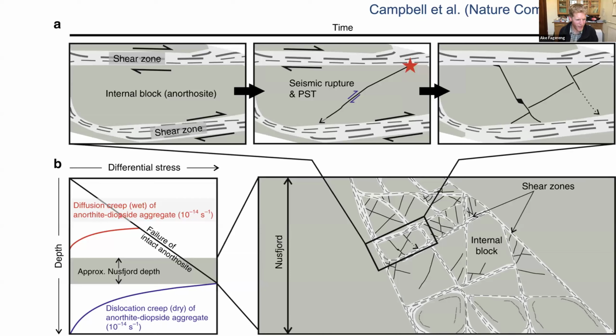Diffusion creep in fine-grained anorthosite with a bit of water in it is quite easy. And these shear zones are generally dikes that are a bit finer grained, maybe a bit wet, or they are resulting from previous pseudotachylites that might have increased permeability and got some water into the system, and also reduced the grain size of the anorthosite. So we have some shear zones that can deform by viscous shear, and internal blocks that can't because they're dry and coarse-grained. So very difficult to deform by diffusion creep, and dislocation creep in anorthosite is difficult at this kind of depth.